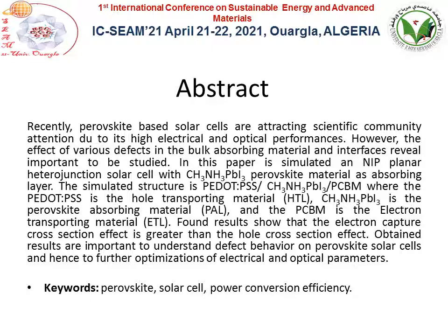The simulated structure is PEDOT:PSS, CH3NH3PbI3, PCBM, where PEDOT:PSS is the hole transporting material, HTL, CH3NH3PbI3 is the perovskite absorbing material, PAL, and the PCBM is the electron transporting material, ETL. Found results show that the electron capture cross-section effect is greater than the hole cross-section effect. Obtained results are important to understand defect behavior in perovskite solar cells and hence for further optimizations of electrical and optical parameters.